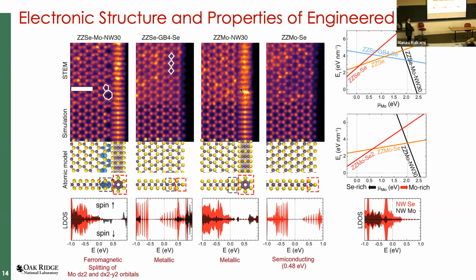It's a semiconductor. So if I can reconstruct the edge right here, this edge has semiconductor-like properties as well. However, if I start to put a metallic nanowire that's enriched in molybdenum, I start to create this metallic element directly at that interface. And similarly, if I'm segregating a little selenium atom as well with this little grain boundary configuration, you can even create ferromagnetic type properties that are engineered at the edge. So I just want you to keep in mind, start with a semiconductor, you can do atomic transformations, you can do atomic engineering, and you can get new functional properties that are highly localized at the atomic scale.